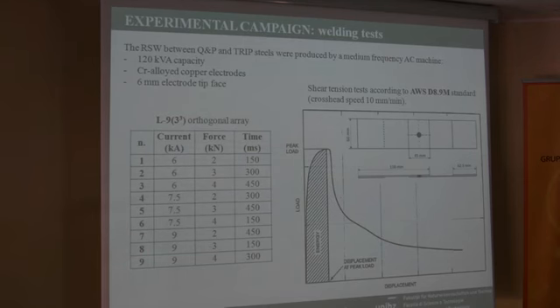In particular, in order to evaluate also the effect of the main important welding parameters on the final mechanical strength of the weld spots, we have applied an orthogonal array considering 9 tests with different process welding parameters, and we have carried out 4 replications in order to obtain consistent results. And so you can see that we have this test where we have low welding current. In this other test, we have medium welding current, and in this final test, we have high welding current. And for each of these groups, we have an increase of the clamping force that was used for the experimental test. So by changing the welding current, the welding force, and the welding time, we have applied this experiment.